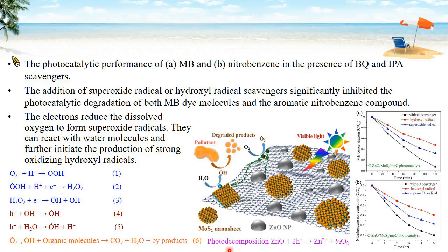We know that under UV irradiation for a long time, holes from zinc oxide nanoparticles in solution could react with surface oxygen and result in the photodecomposition of zinc oxide. In our composite, holes from the embedded zinc oxide are consumed in the photocatalytic reactions, and the competing dissolution process of zinc oxide can be suppressed.